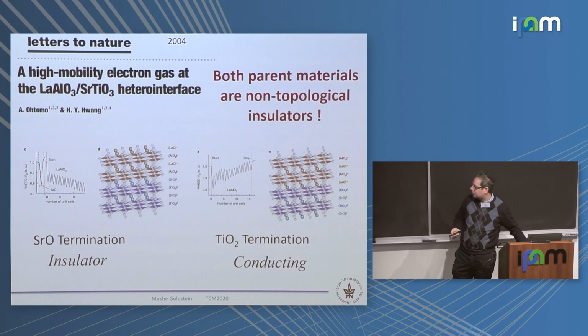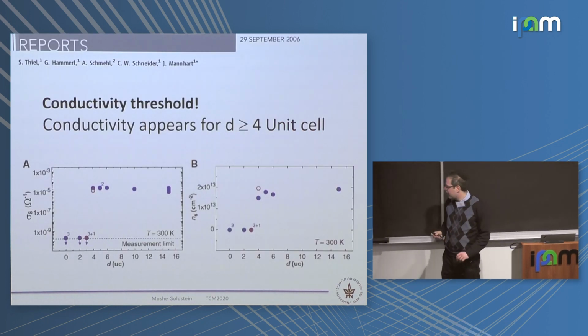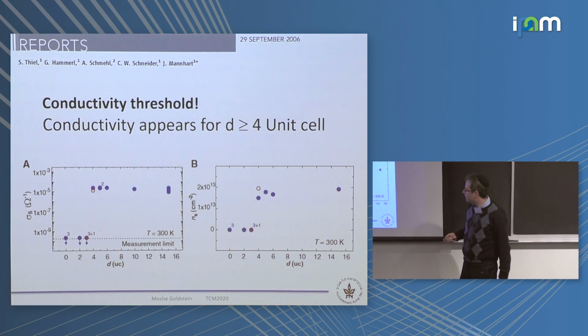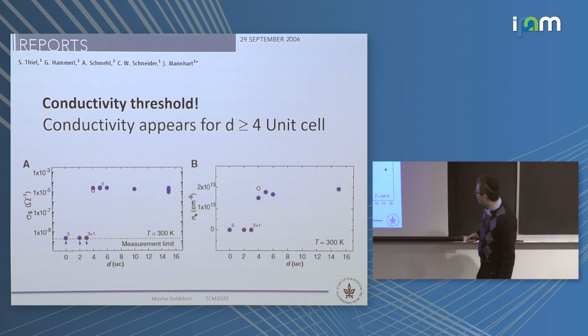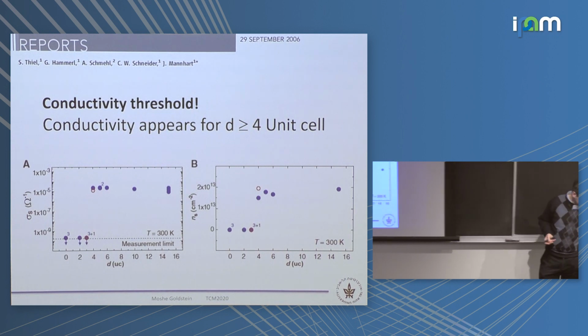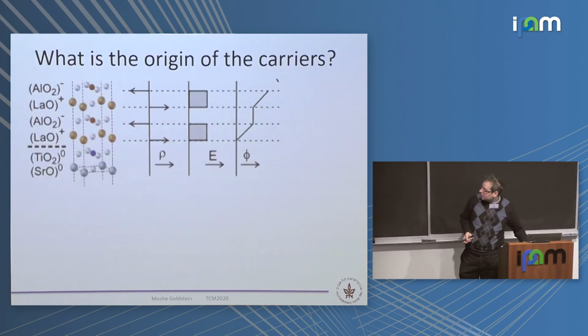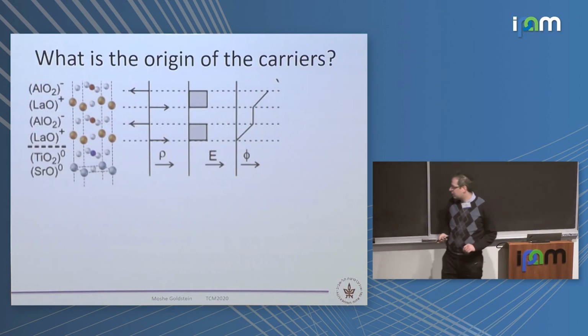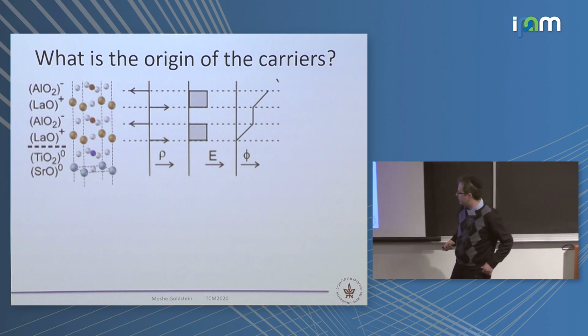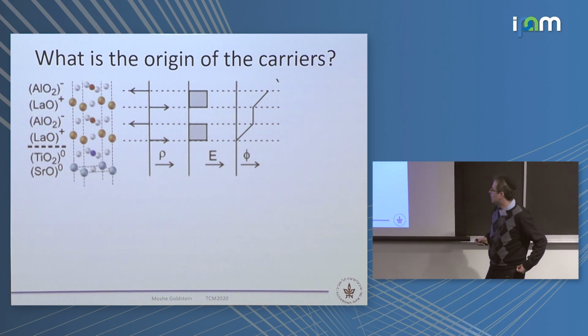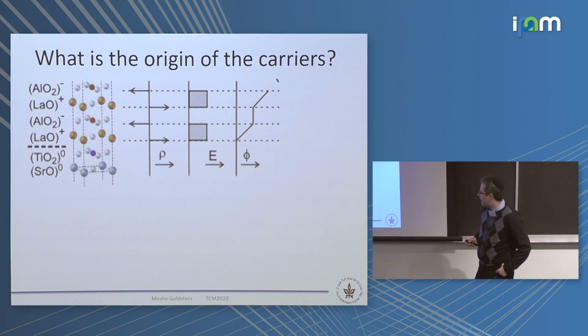So it's 2 insulators. They are not doped. They are not topological, so it's not some topological edge modes. Yet you get conduction. And it turns out that you need a minimal number of 4 unit cells of lanthanum aluminate to get conduction. And what is the reason for that? People believe that the reason is actually very simple. It is what is known as the polar catastrophe.